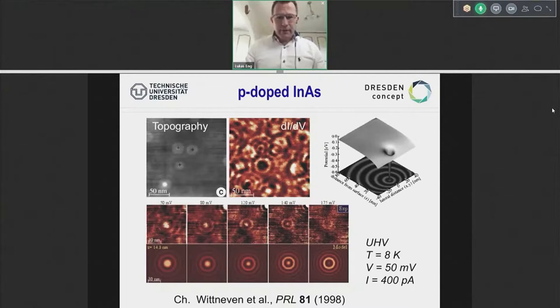And this is exactly one way to analyze. So coming back means, yes, these are buried defects and not at the top surface, they're somewhere in the system. By analyzing this kind of sequence of waves at the surface, cutting this surface like shown here, you're able to really even say something about the chemistry of that defect, which is buried within your sample, in this case in your material. Splendid work, done though at 8K. So that's the only drawback. You have to do such an experiment at low temperatures.